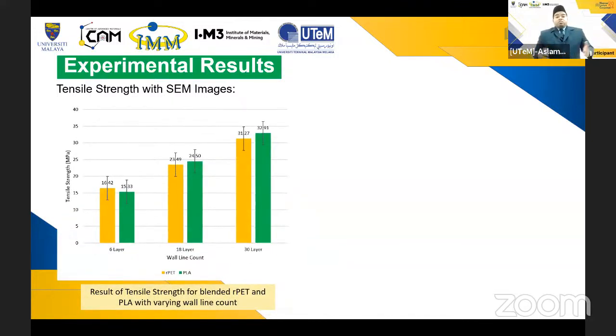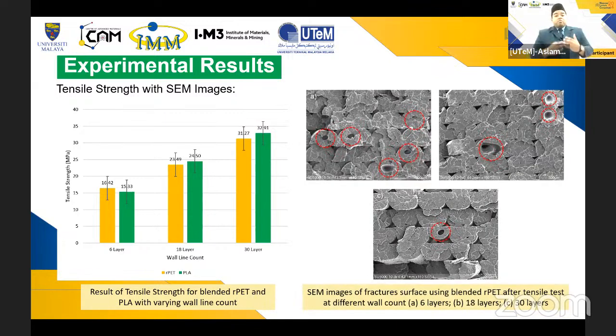So here's the experimental result showing the tensile strength of the blended rPET. As you can see on the bar chart on your left, the blended rPET increases in tensile strength with increasing wall line count. This also shows that the blended rPET is comparable with PLA in terms of tensile strength. These FESEM images also show that increasing wall line count can reduce the voids and porosity within the sample, supporting the tensile data.